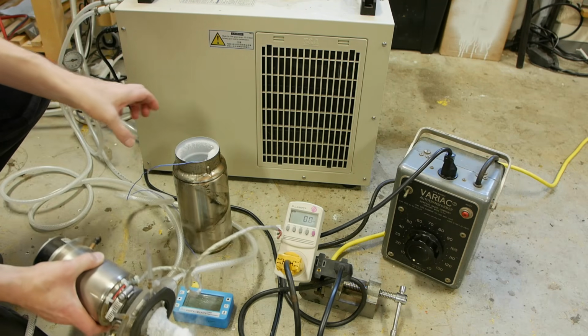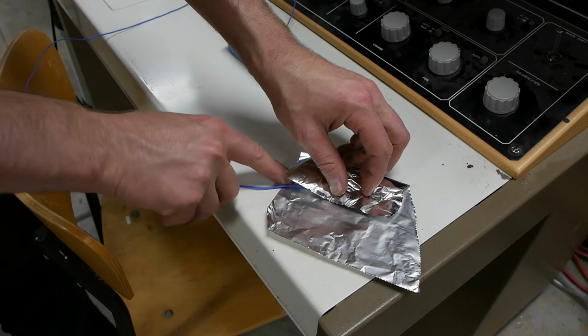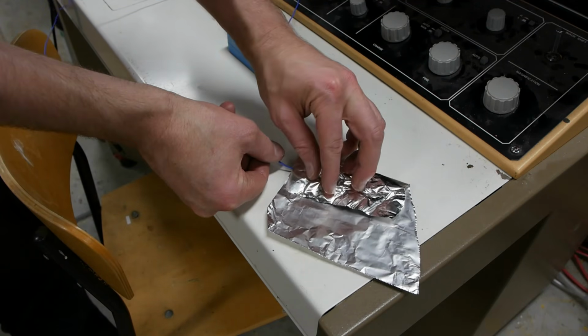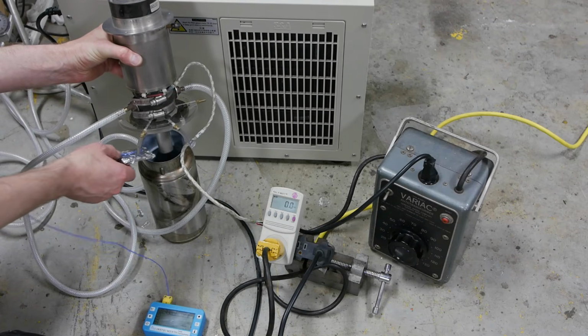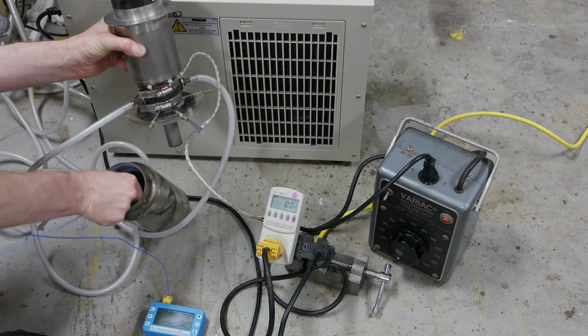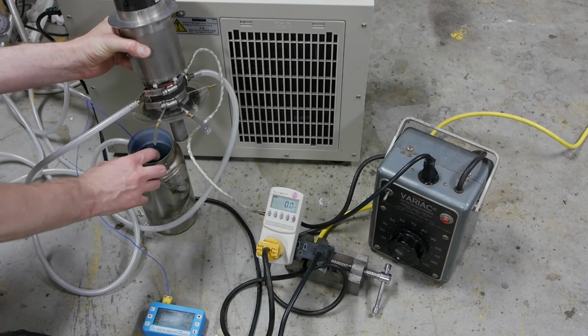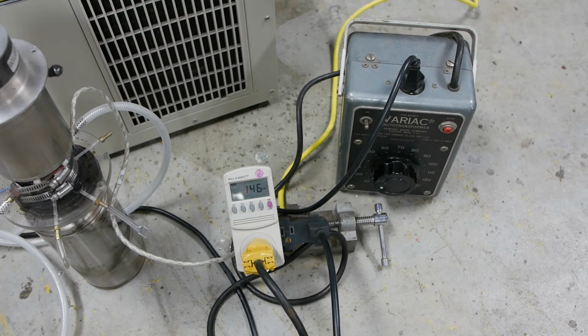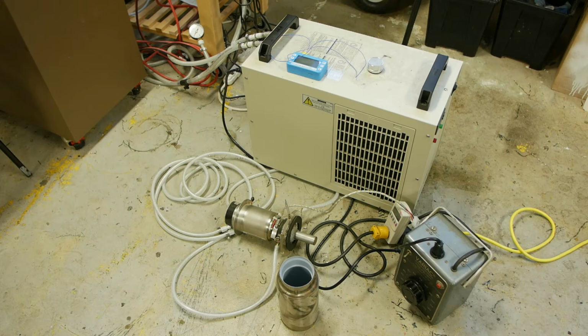So lucky me, I actually have a cryo cooler that generates liquid nitrogen on demand. So I took the bits and put them into a little foil pack with a temperature probe and put them into a vacuum flask, and then put this cryo cooler on top and used a variac to power up the cryo cooler slowly. So eventually this cryo cooler uses about 150 watts and will drip liquid nitrogen off the end of it and down into the flask. I have a video on my liquid nitrogen generator if you want more details on this.